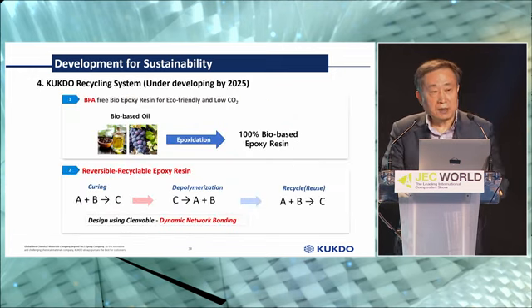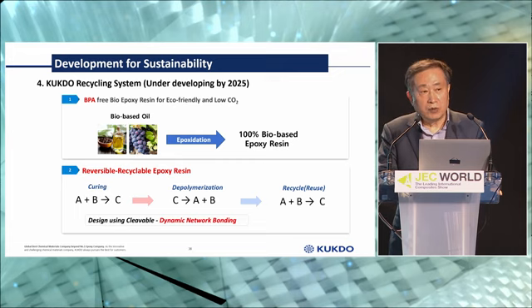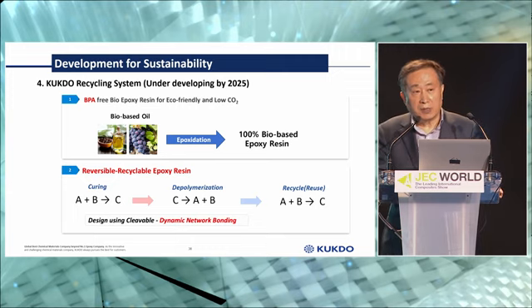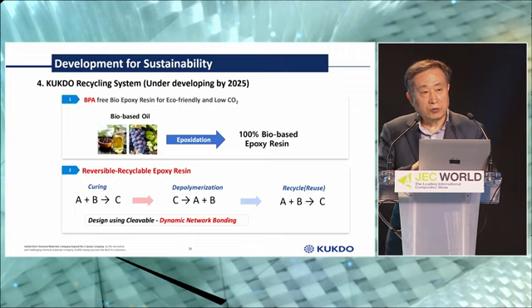So Kukdo recycling. Now carbon composite or glass fiber composite is being used for many applications. And now like wind energy, wind blades, after 25 years we have the concern about recycling. So we want to have an easy and low cost recycling system based on different chemistries, 100% bio, self-degradable epoxy systems, but which have good enough mechanical properties. So now Kukdo is introducing to the market, for sustainability, bio-based epoxies, and developing bio-based epoxies. And we are co-developing with a university, and there is a company, KCTech in Korea. They are very strong in recycling technologies. So we are introducing self-degradable or bio-based epoxy, which is easy to decompose, and then they are developing the process.